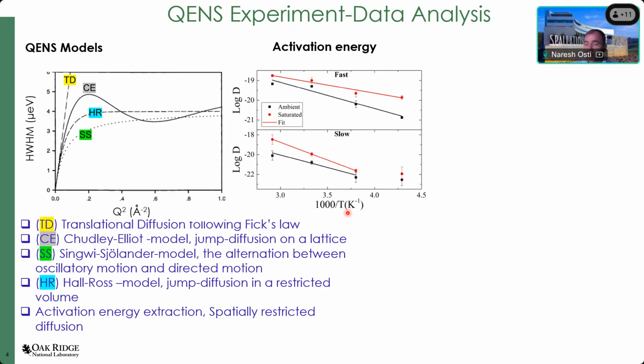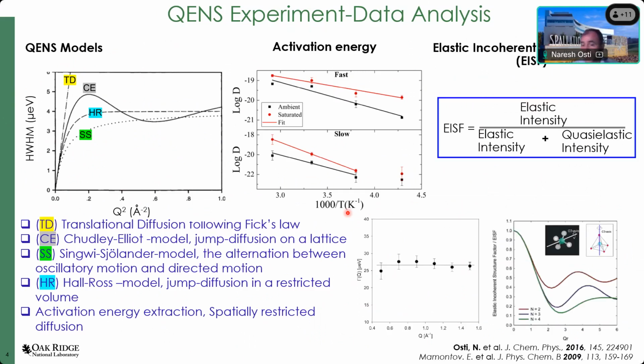Now, there is another piece of information that you can obtain from this technique. If there is no Q dependence of the half width at half maxima, that means if you plot the half width at half maxima as a function of Q and you end up with a flat nature, that means there is an absence of long-range translational diffusion of moving species in your system.